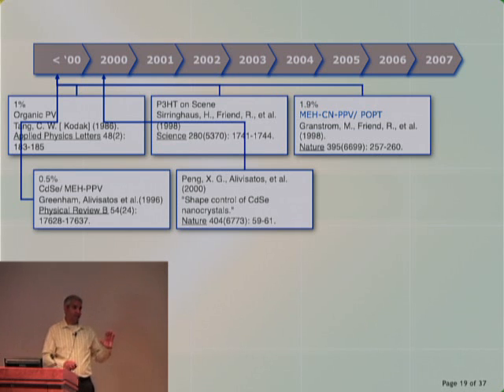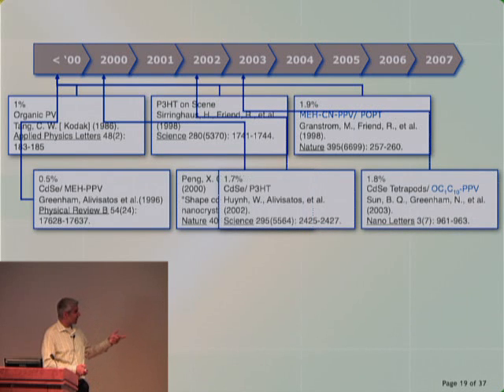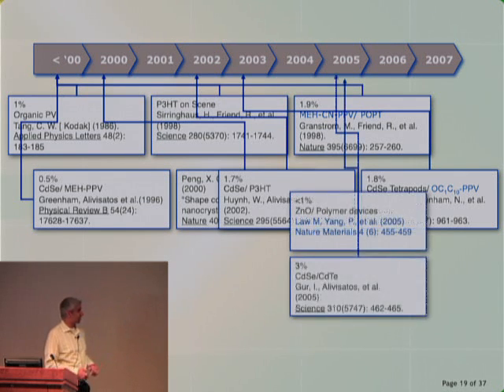So they said, look, okay, maybe we don't get a great efficiency right now, but that's because we have these dots, these spheres. Maybe what we should do is actually work on synthesizing actual natural percolation networks in our material so that the chemistry solves the efficiency problems. And so that went on for many years, and still today, we didn't really get very far on what I'd call a hybrid thread. We got to maybe about 2%, but there are certainly some issues there.